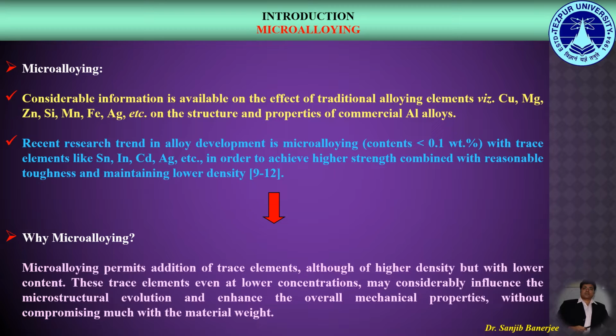Regarding microalloying, the recent trend in alloy development is microalloying, where contents would be less than 0.1 weight% with trace elements in order to achieve higher strength combined with reasonable toughness and maintaining lower density. The reason behind microalloying is that it permits addition of trace elements, although of higher density, but with lower content, and these trace elements even at lower concentrations may considerably influence the microstructural evolution and enhance the overall mechanical properties but without compromising the material weight.